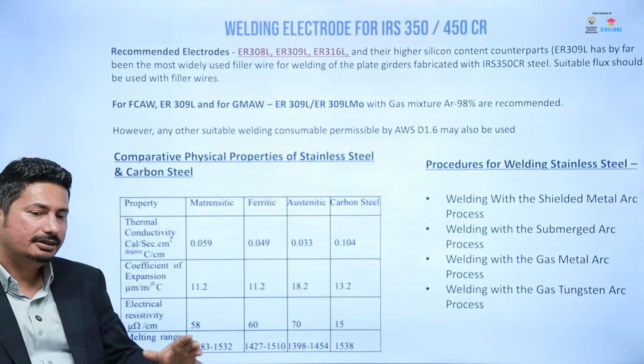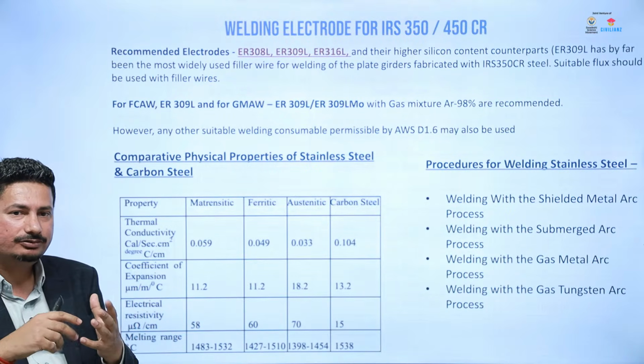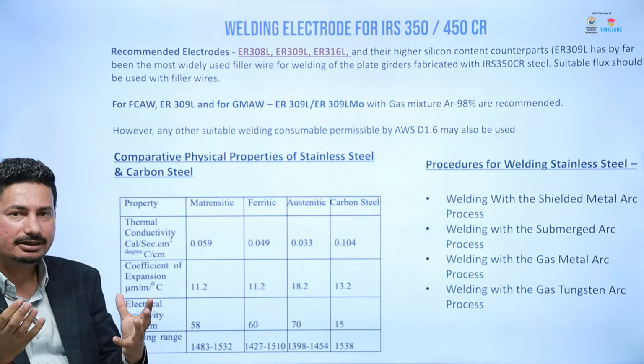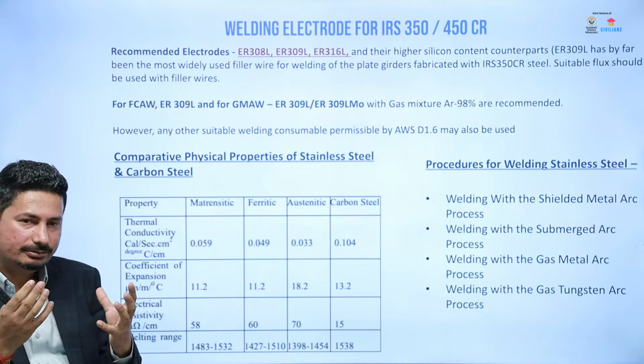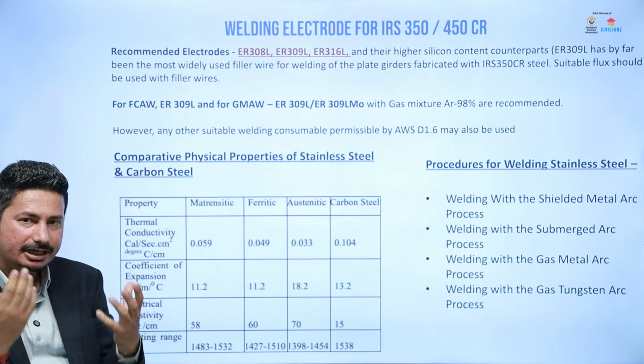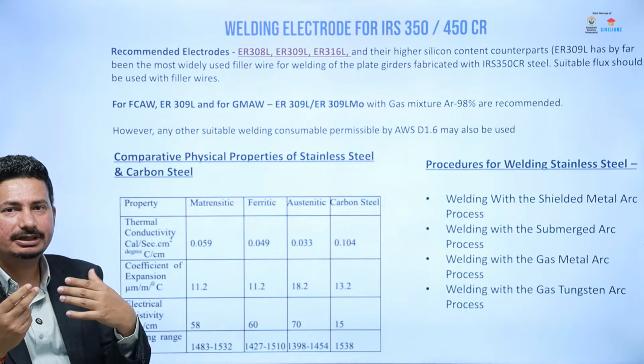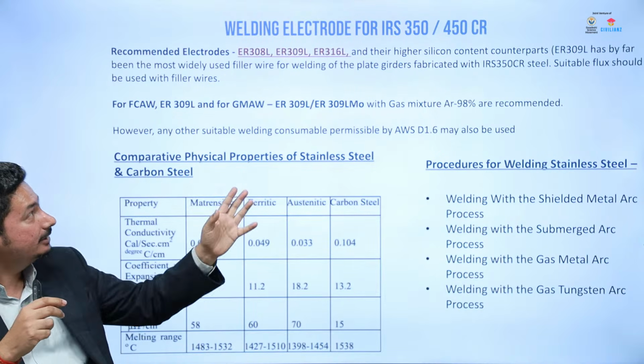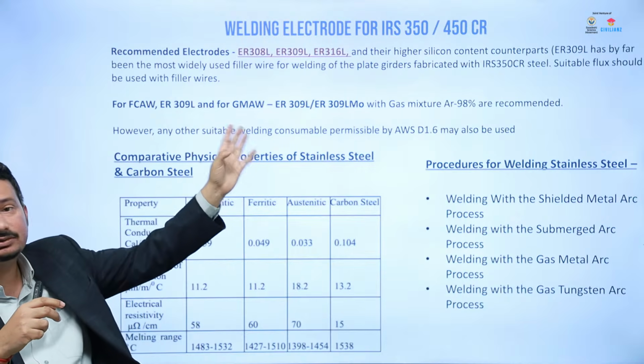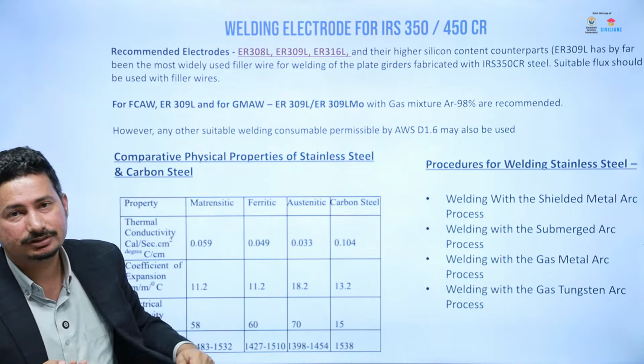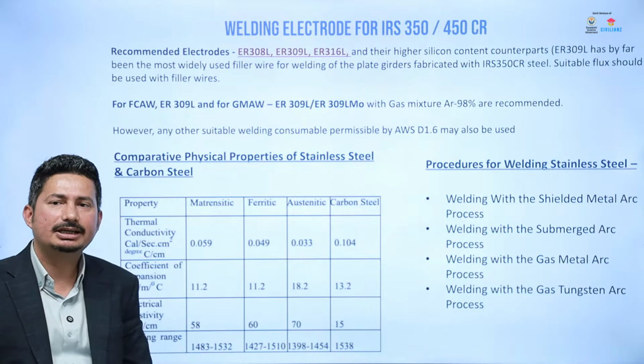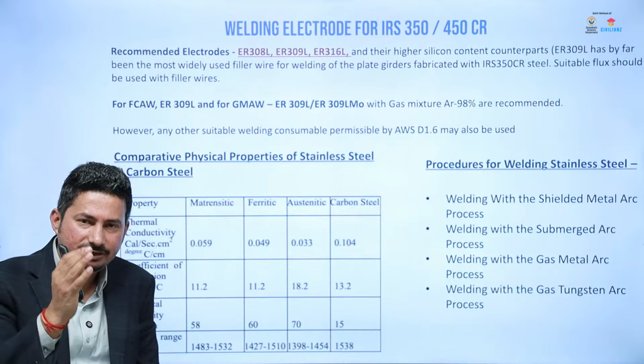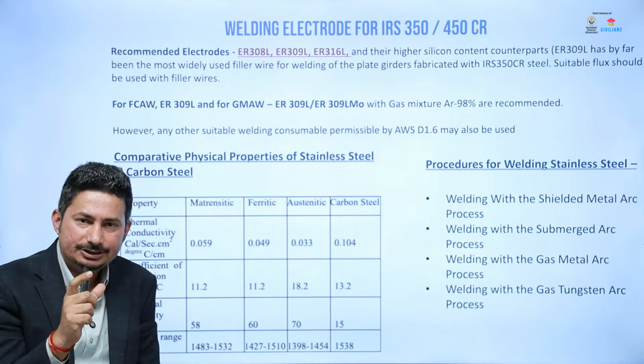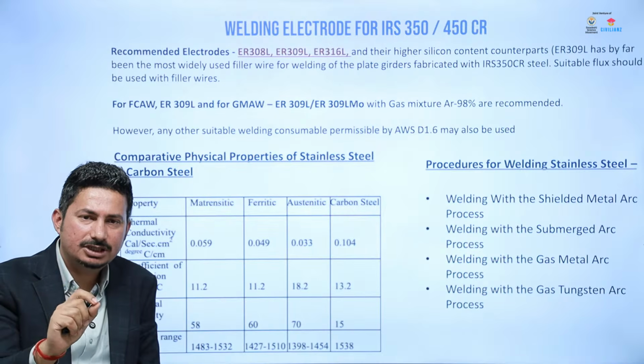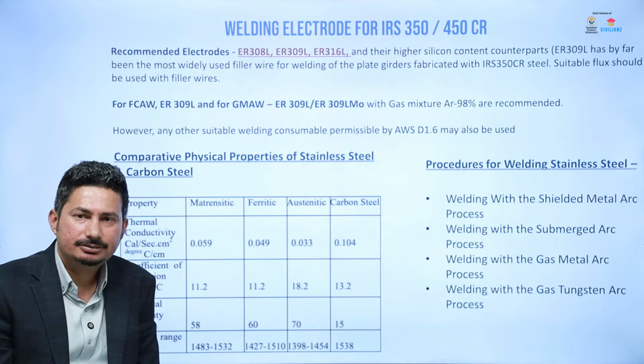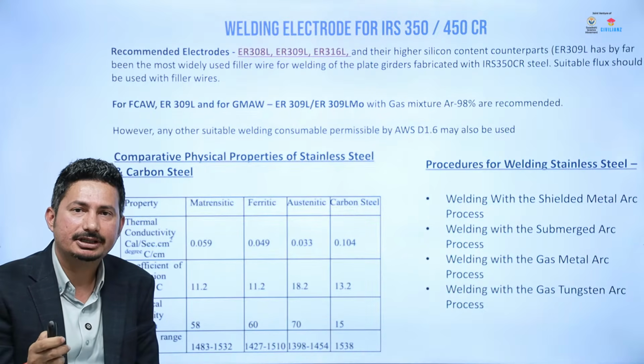When it comes to welding, generally we ask this question: if we are going for welding of stainless steel, will it be very, very different? It's not very different. The same machine can be used, the same manpower can be used. Only the electrode changes. For example, if we have to weld stainless steel, the grades of electrodes are 308L, 309L, and 316L, based on the different grades of stainless steel. The most commonly used welding electrode is 309L, and the same welding procedures will be used. Only heat input has to be controlled, and with minor training, the same person can weld using the same welding machines, if I put it that way.